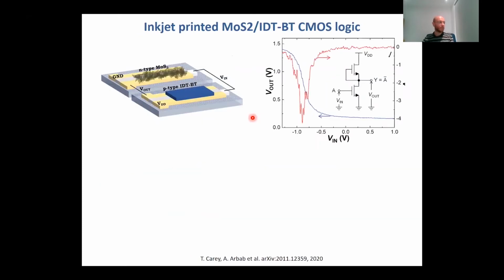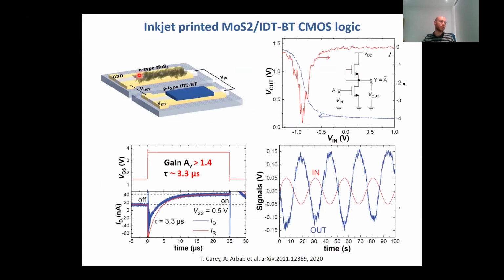And then we can also combine this technology, the MoS2 printed technology, with organic electronics printed devices. In this case, we are showing compatibility of hybrid devices with existing organic systems and 2D material systems. So this gives us, for example, inverter designs with very fast response. We're looking at around 3.3 microseconds. In the case of graphene, we were getting up to even milliseconds. So these devices are much faster than what we obtained previously. And also we can see that there is still an amplification of the signal, even working in AC.